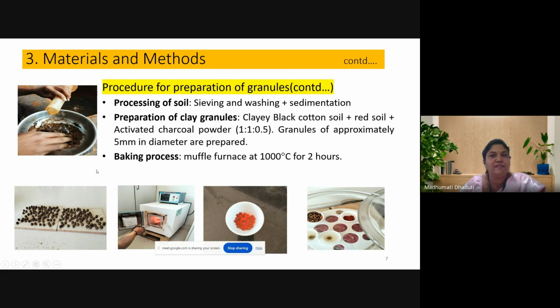dried in the oven, and then they were baked in the muffle furnace at 1000 degrees centigrade for 2 hours. So you can see here in the crucible that they are red hot, and finally they were cooled in a desiccator and brought to room temperature, and further the granules were characterized before adsorption, and they were also used for adsorption, and they were characterized.